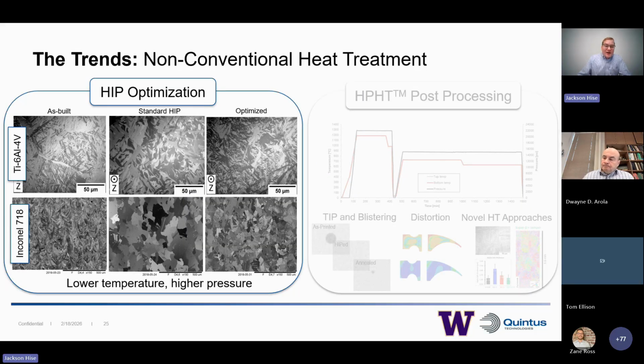Another trend is non-conventional heat treatment. This is really lower temperature, higher pressure than we've seen in the past. As I mentioned, castings have undergone HIP for many decades, and traditional HIP variants might not apply to the additive type of part. So here, if we're looking at Ti-6Al-4V or Inconel 718, using these traditional HIP parameters for cast variants, we see that coarsening of our microstructure.